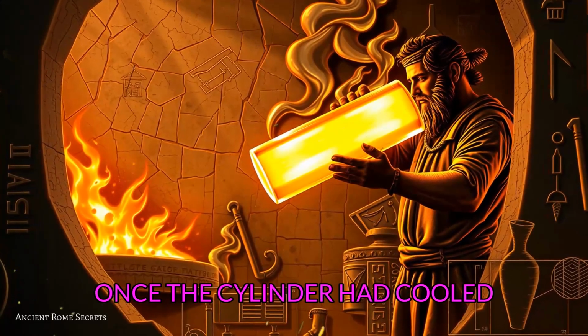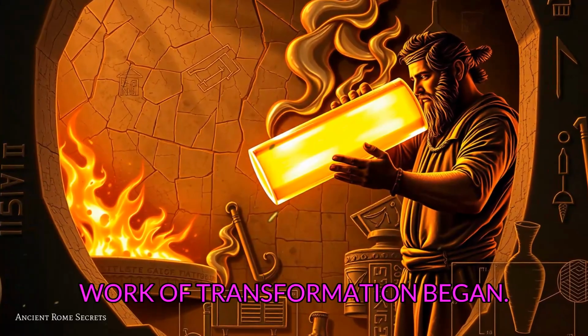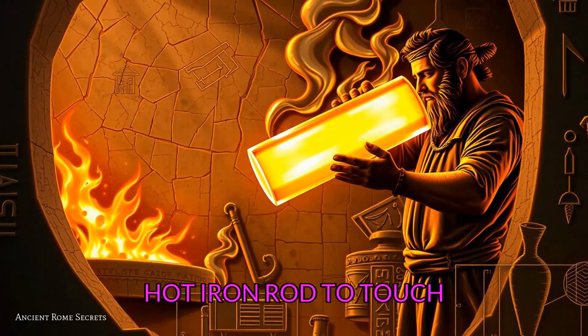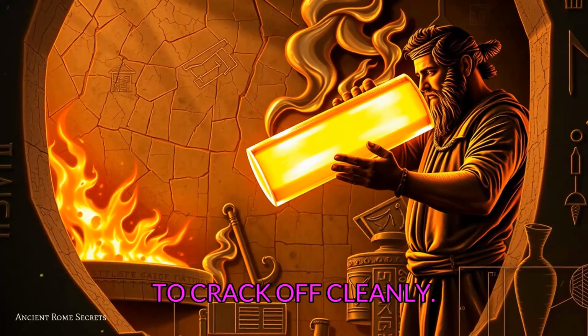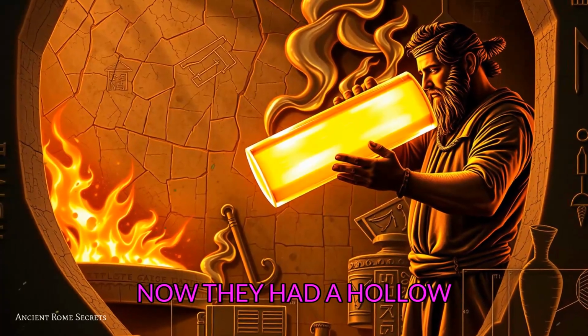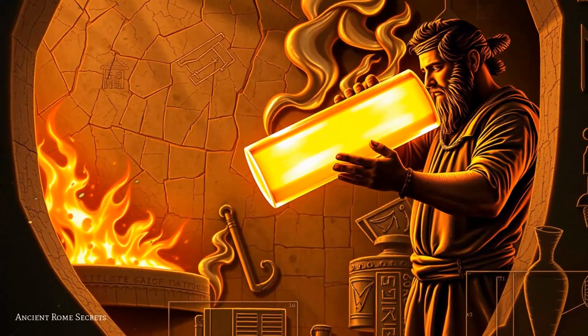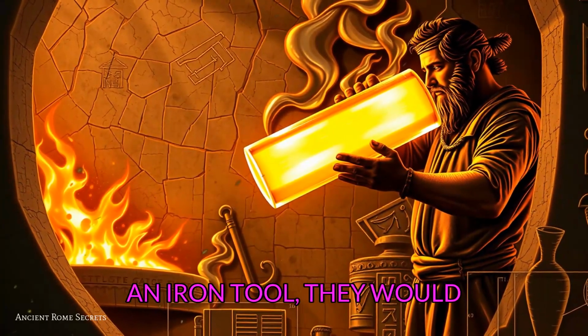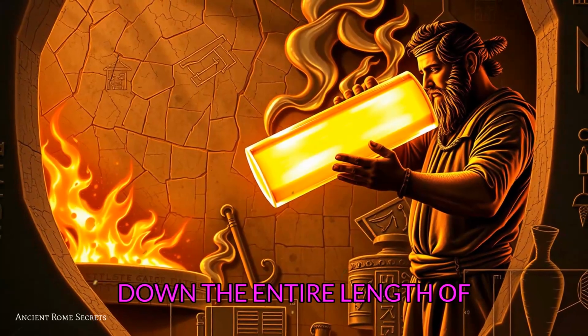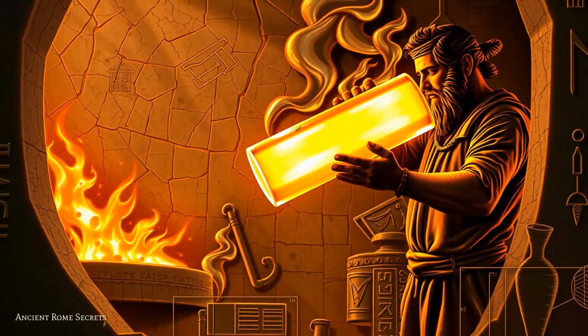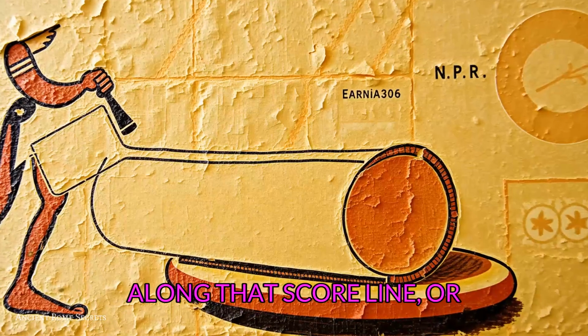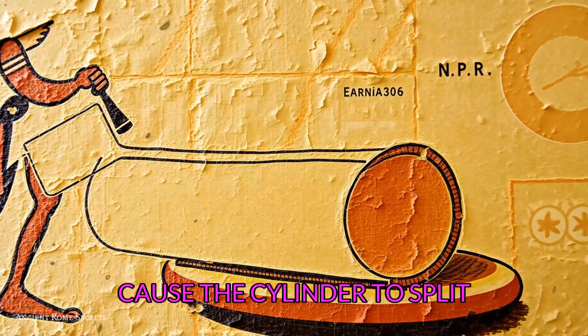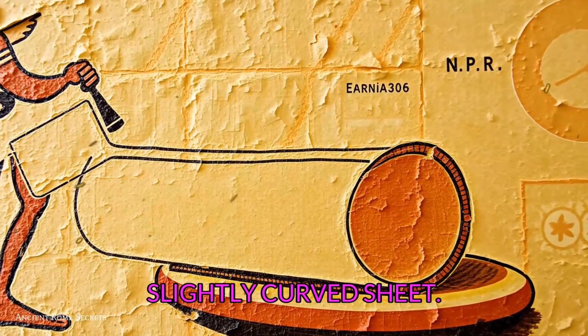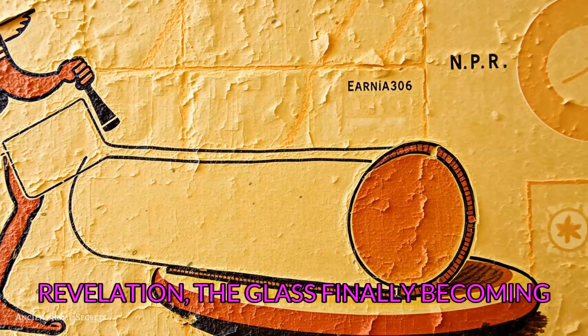Once the cylinder had cooled and hardened completely, the delicate work of transformation began. A worker would use a hot iron rod to touch the sealed ends, causing them to crack off cleanly. Now they had a hollow glass tube. The next move was an act of precision. Using a sharp diamond or an iron tool, they would score a single, continuous line down the entire length of the cylinder. A careful application of heat along that score line, or sometimes just gentle pressure, would cause the cylinder to split open with a quiet crack, uncurling into a single, long, slightly curved sheet. This was the moment of revelation, the glass finally becoming a pane, but it was still curved.